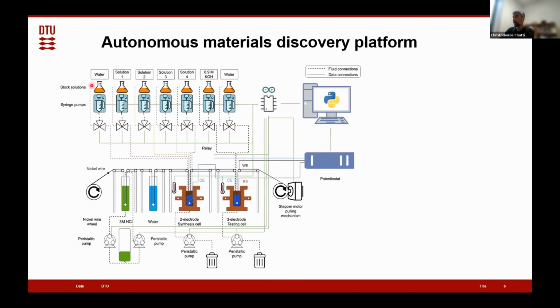We have a set of stock solutions, each coupled with a syringe pump that can then very accurately dose and mix a number of these stock solutions and supply them to the synthesis or testing or prepping stages. This is the roll-to-roll system here, guided by a stepper motor that pulls the substrate, which for the case of alkaline electrolysis was just a nickel wire. And then it's passing through an acid bath where this is being cleaned and then cleaned with water before it goes into an electrodeposition stage where different components are mixed.